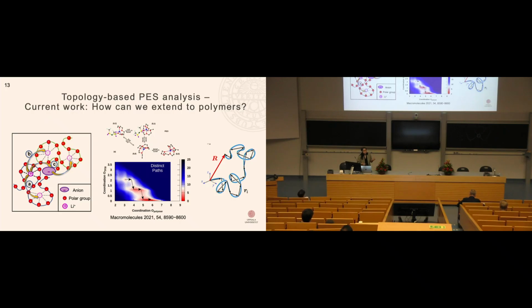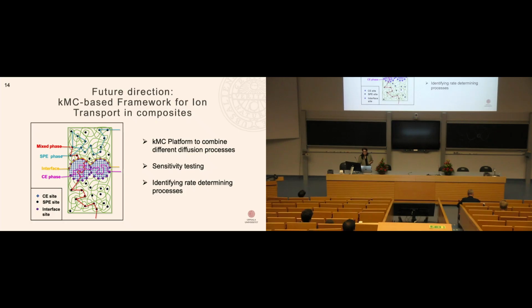And one of the main benefits of these approaches, both for the ceramics and for the polymer here, is that we convert the different processes into the universal language of probabilities. And the power of expressing the different processes as probabilities, and using, for example, a framework like kinetic Monte Carlo, is that we can, in a fairly straightforward way, combine different diffusion processes, although they may occur on very different length and time scales, or are described on very different levels of detail.